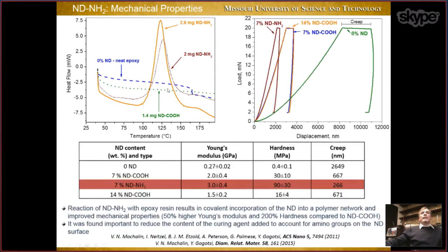So it reacts with epoxy, and we form these covalent bonds, and how it translates into mechanical properties is shown here. This is a nanoindentation experiment, and the parameters extracted from it are listed in the table, and you can see that Young's modulus improves upon addition of 7% of aminated nanodiamond, while compared to epoxy, the improvement is about 10 times or so. Compared to carboxylated nanodiamond, it's still 1.5 times improvement in Young's modulus. But then if you look at hardness, for example, the improvement in hardness is 300%. So it's 3 times improvement compared to non-aminated material.